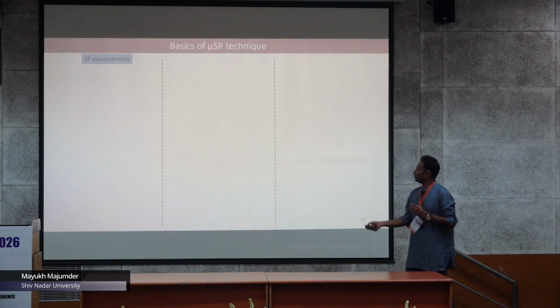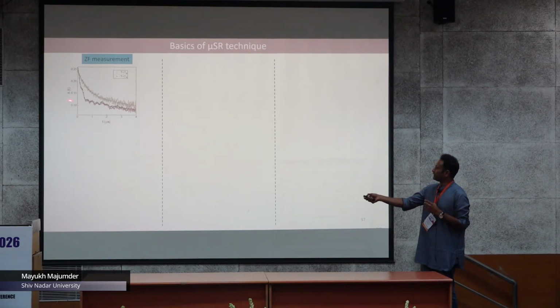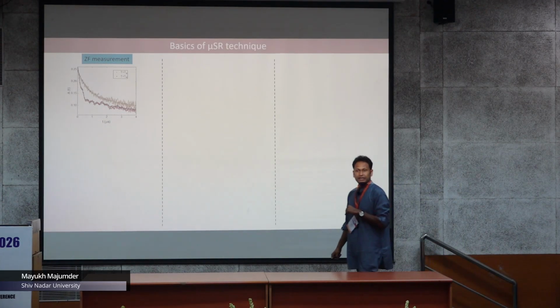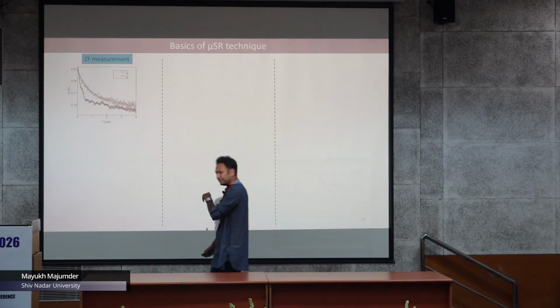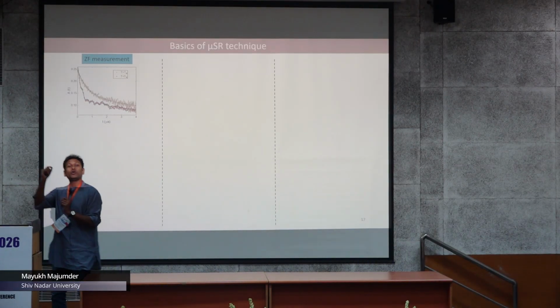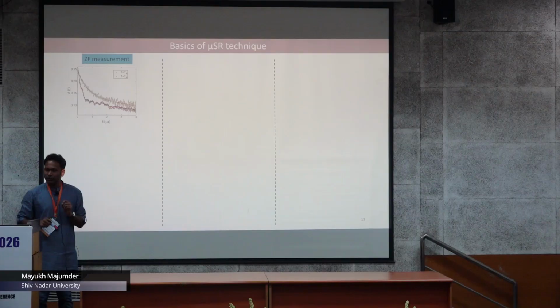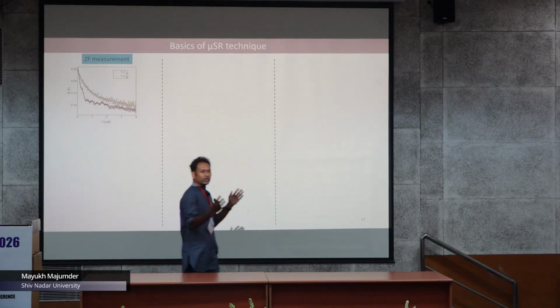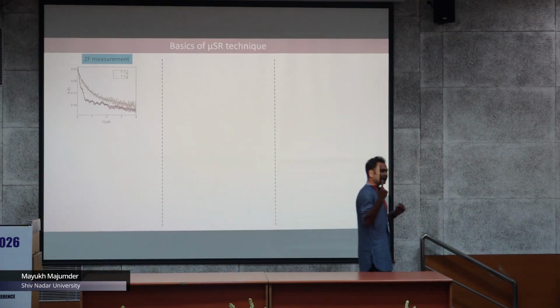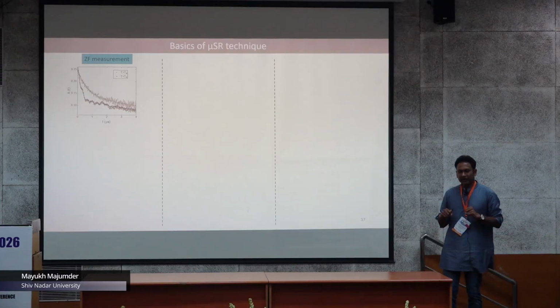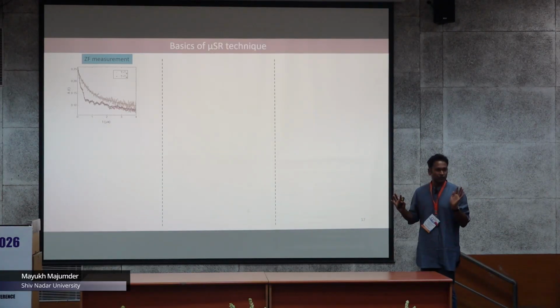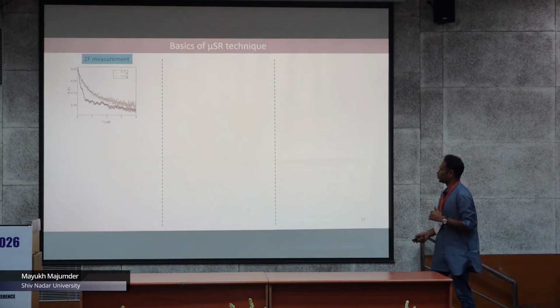And in the muSR data, you would be expecting that you can see the muon asymmetry as a function of time. Please look at the lower curve, there are some oscillations present. If you take the Fourier transform of it, you get the local field that the muons are experiencing at the muon site. Okay, so if there is no oscillation, there is no ordering, you can say, and it can detect static ordering which is of the order of 1 Gauss. Okay, so it is very good at that.